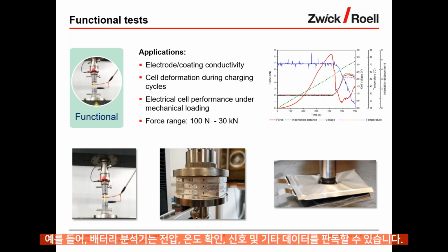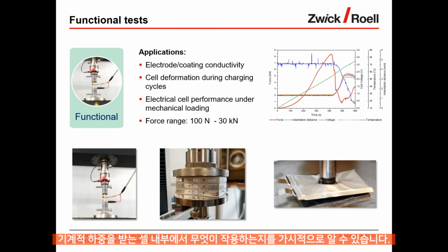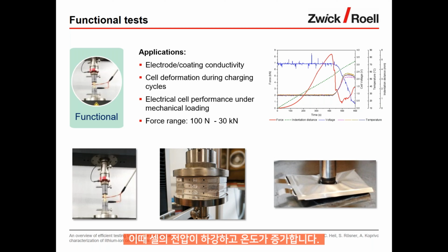For example, from a battery analyzer, we can read in voltages, we can read in temperatures and other data or other signals. And you see in the graph that we can superimpose them and actually get a very good picture of what is happening inside a cell during a mechanical loading. So as here the mechanical loading increases, at one point the cell goes into a short circuit, so the cell voltage drops. At the same time, the cell temperature increases, and all this can be documented and recorded with our system.